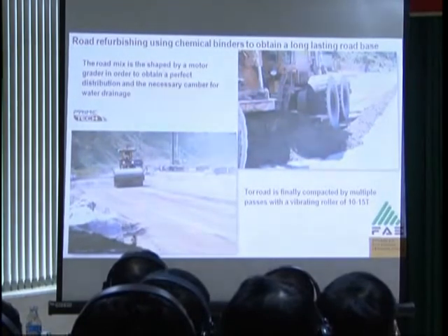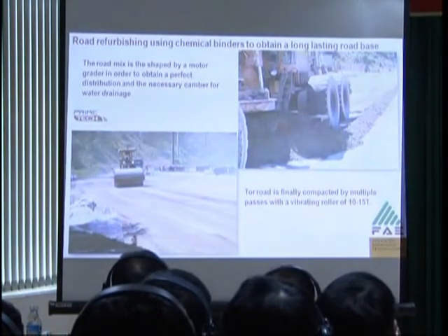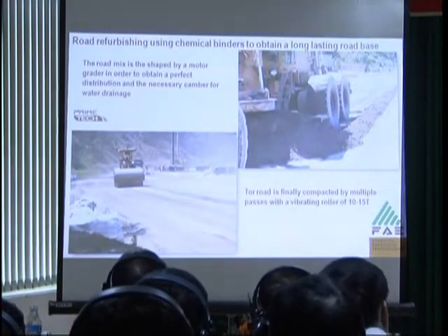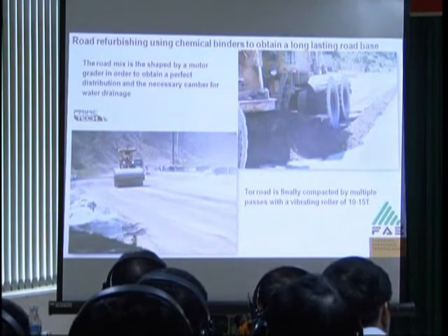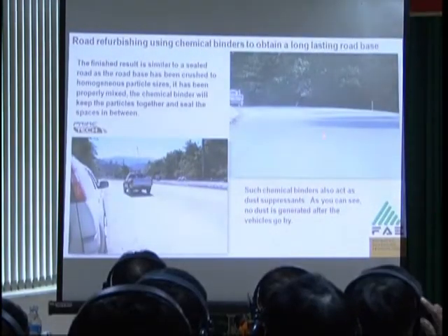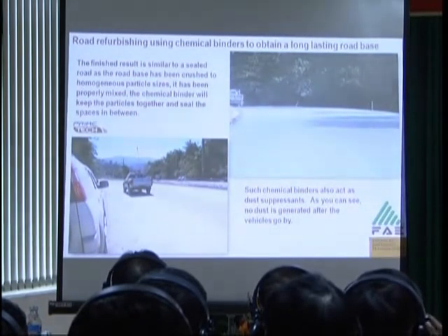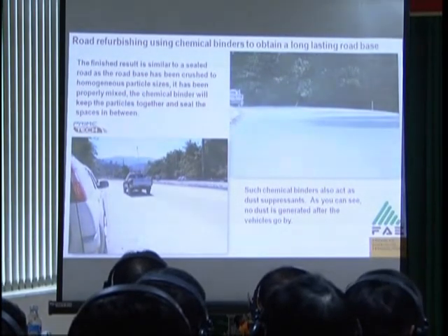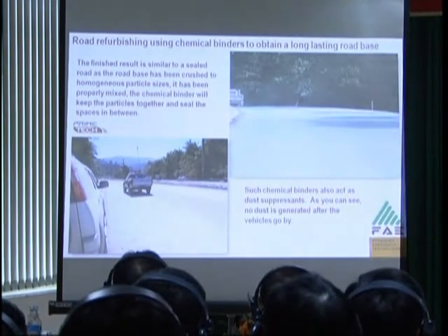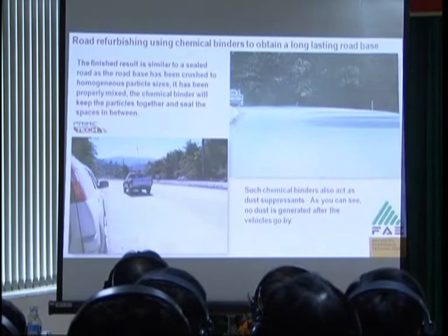Once the material has been sprayed with water, the rocks have been crushed. The same thing they do, they give a shape, always give shape to the road, and then finally they compact with a vibrating roller, and this is a finished road. See? This road looks very good, looks like a cement road, but there's no asphalt here, only chemical product, concrete, a little bit of sand, chemical product, and crushed rocks.